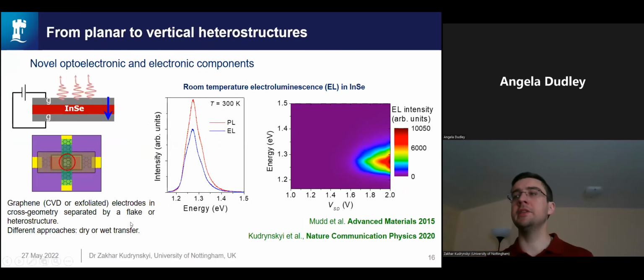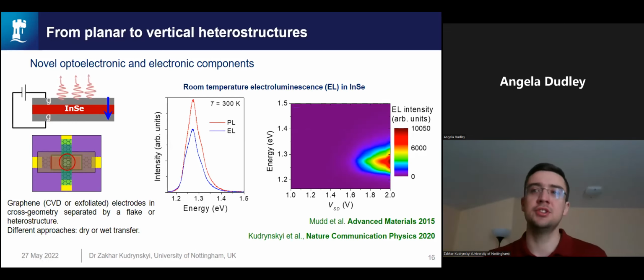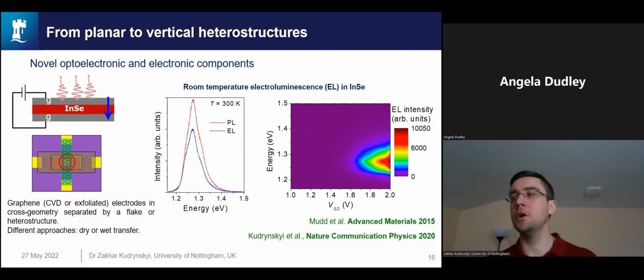And we also looked at other geometries, which is a vertical geometry. So rather than to have two graphene electrodes in plane, we have a top and bottom graphene electrodes. And in this case, with a PN junction we can realize a detector that works without any applied bias, basically self-powered due to the built-in electric field by this junction. But this vertical structure is interesting not only because of the possibility of photosensing, but also of generating light. So recently we have been looking at the electroluminescence in this type of geometry.